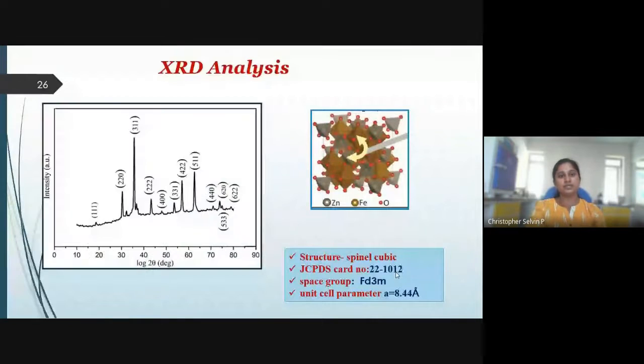As mentioned earlier, initially structural analysis was made by means of XRD analysis. The XRD pattern shows sharp and well-ordered diffraction planes, which indicates the high crystalline nature of the prepared samples. All the samples were indexed to the spinel cubic structure, that is cubic symmetry, without any detected impurity of secondary phases, which indicates that a phase pure sample is practically achievable by means of the green synthesis route. The present sample is in line with JCPDS card number 22-1012, which lies in the space group Fd3m, and we could calculate the unit cell parameter, which is 8.44 angstrom.